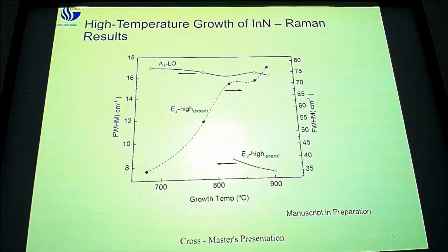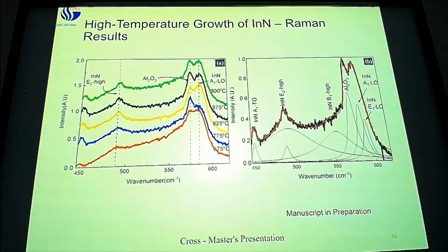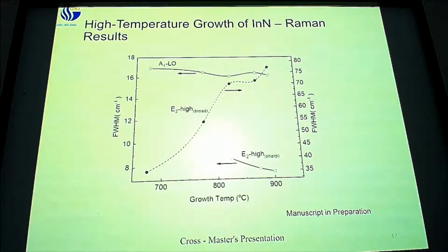We can see here the E2 broad and the E2 high peak. Going back here, we defined two peaks because it was modeled better by two peaks, and we have evidence that shows that. If we look at the E2 high peak here, it decreases as we go to high temperature. That means that the crystal quality gets better. Yes, full width half max, sorry. That is clearly labeled there, even if I got it wrong. So the full width half max of the peak decreases here, and what that means is that the crystal quality gets better as we go to higher temperature, which is nice. That's exciting. We want better crystal quality. But we still have a second E2 peak that does the opposite thing, so we need to understand that as well.